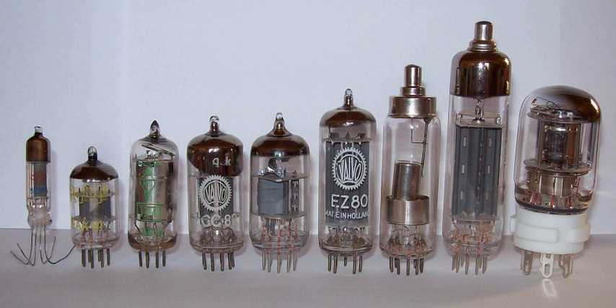The end-of-life scenario for a thoriated tungsten filament is when the carbonized layer has mostly been converted back into another form of tungsten carbide and emission begins to drop off rapidly. A complete loss of thorium has never been found to be a factor in the end-of-life in a tube with this type of emitter. WAAY-TV in Huntsville, Alabama achieved 163,000 hours, 18.6 years, of service from an Eimac external cavity klystron in the visual circuit of its transmitter. This is the highest documented service life for this type of tube.